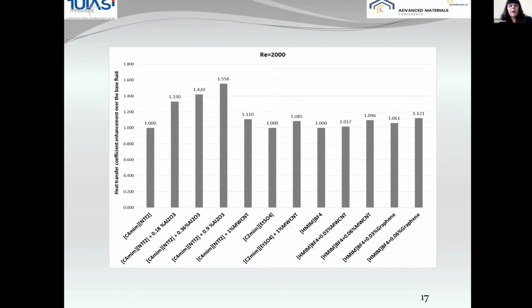Here you have also another plot that can help you see the heat transfer coefficient enhancement over the base fluid. Here is the base fluid, and this is with the addition of alumina and other nanoparticles. You can see here that the enhancement goes up to 56%, but it depends mostly on the ionic liquid that was used as base fluid and also the nanoparticle type and concentration.